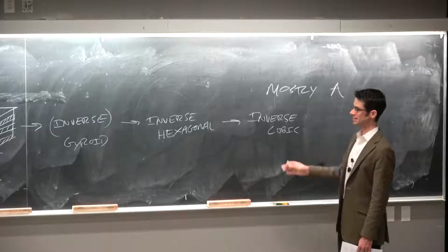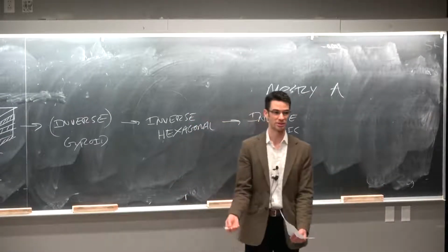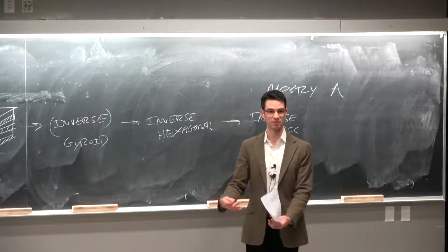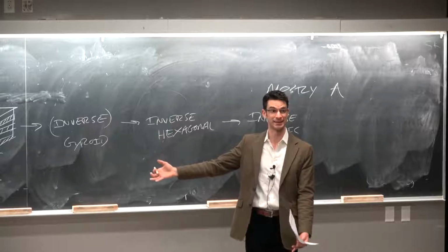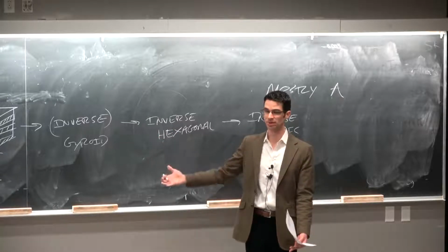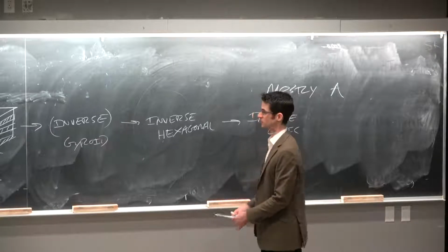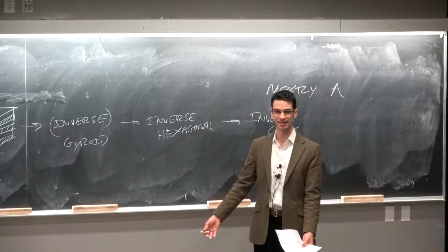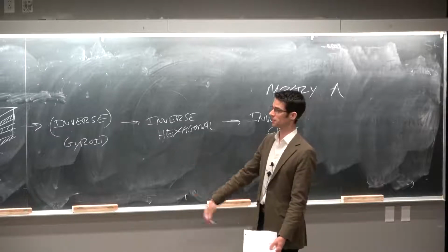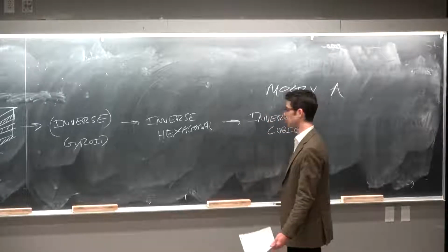So these processes are used, why are they bottom up? Because we start with a chemical structure and we anneal the film or we treat it in a certain way and it grows into these structures automatically, just based on the molecular design and the thermodynamics. It forms a structure automatically. We didn't have to do any lithography. We didn't have to etch anything. And these structures are useful for a wide variety of technological applications.